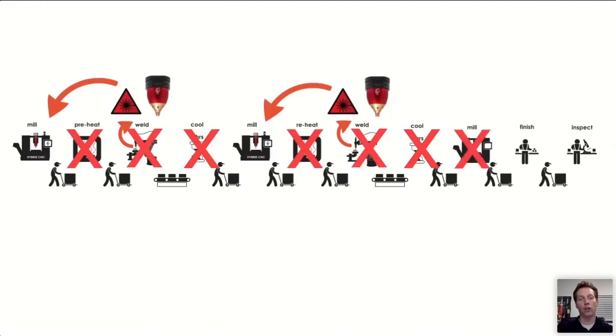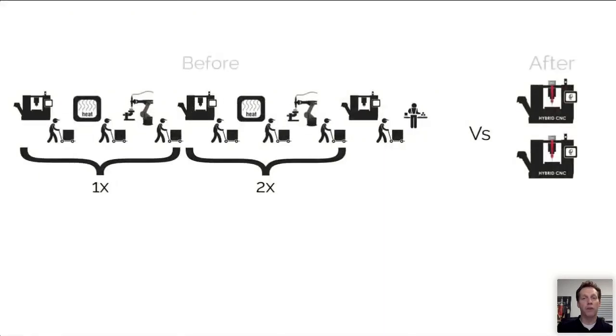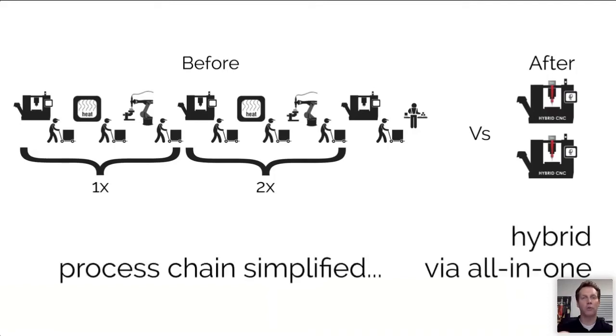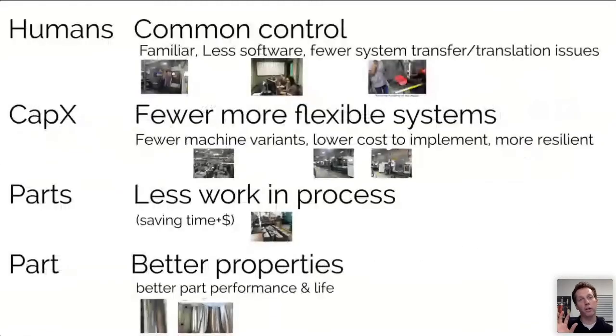And because now we're all common in a milling machine, and we can bring multiple processes to these parts, we can actually eliminate every one of these transfer steps until the part comes out of the machine to go downstream for final inspection. So in that way, we really bring a before and after that's a tremendous boon and boost to efficiency by consolidating those things into a couple of hybrid all-in-one machines. And so this is another process simplified by hybrid all-in-one.